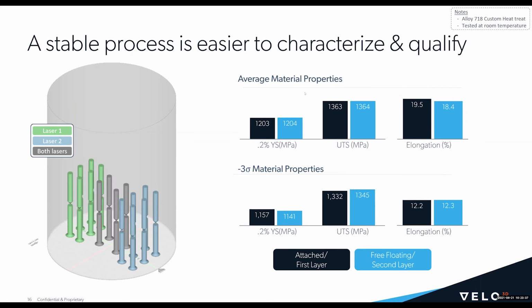So basically what we're doing with the plots here is we're verifying, you can see here on the left side of the screen, a layer of attached bars to the build plate, a layer of free floating bars above that, and then also laser 1, laser 2, and dual laser bars. Dark blue is the attached and first layer. The light blue is the free floating or the second layer. And you can see consistency both in the average and the -3 sigma properties between these two different data sets.